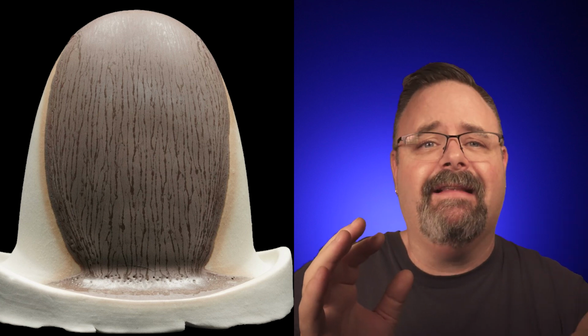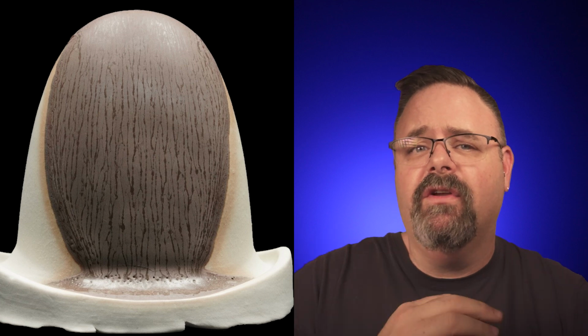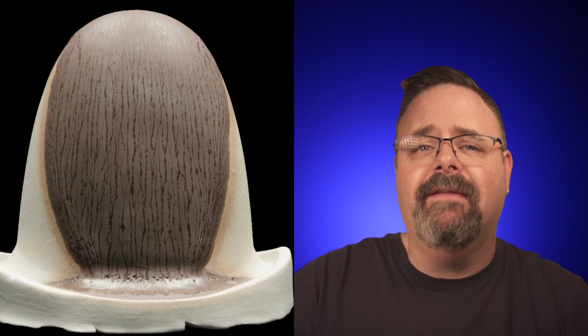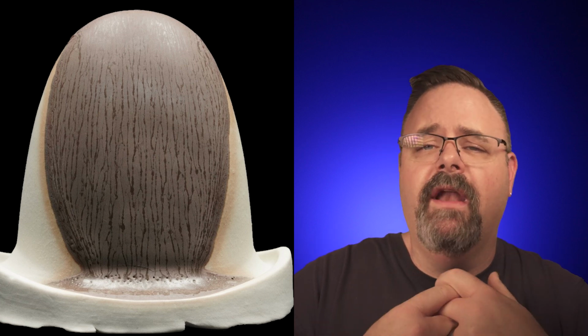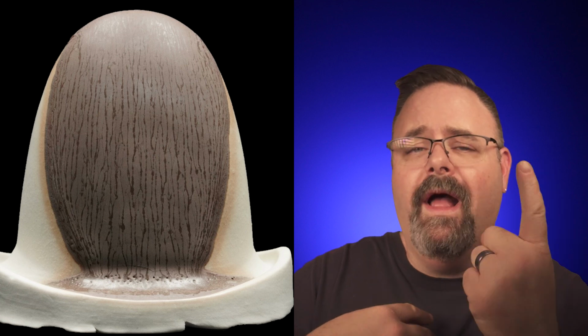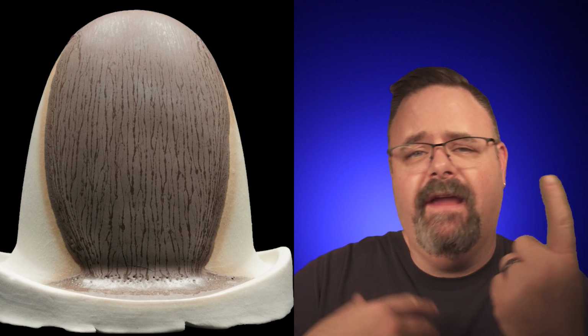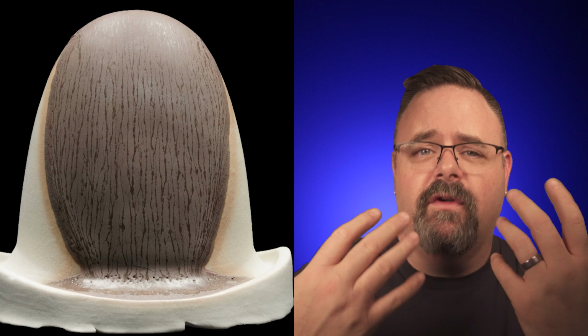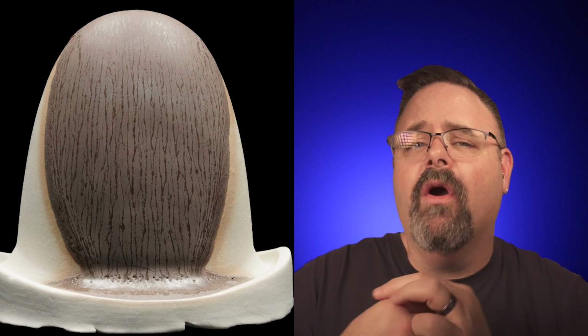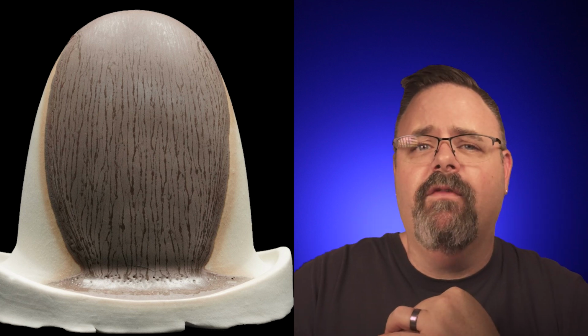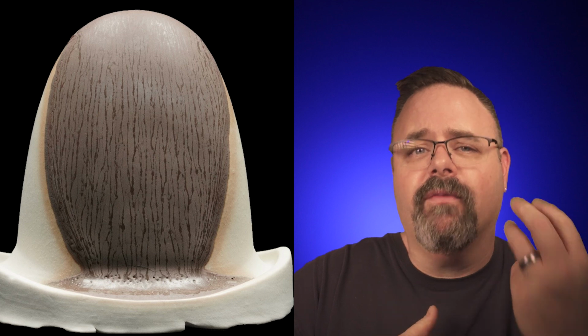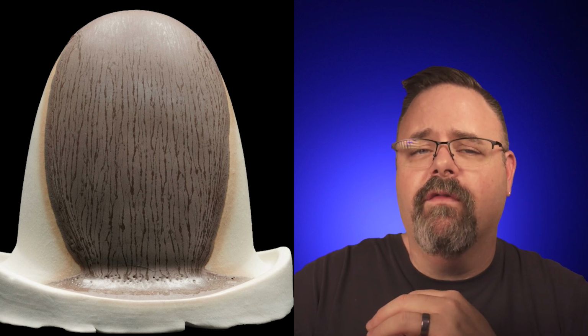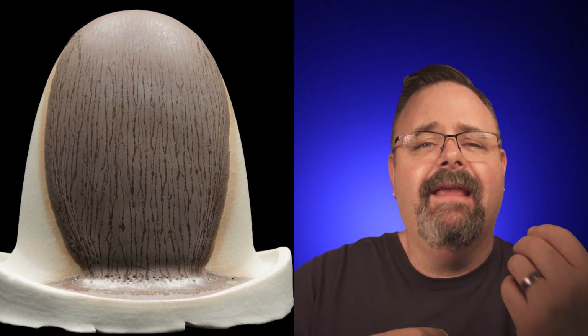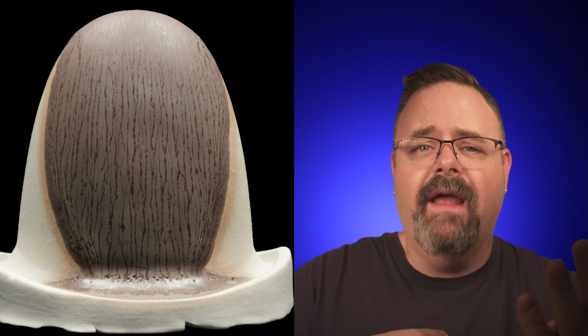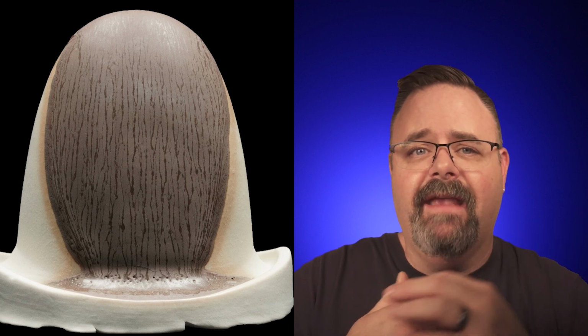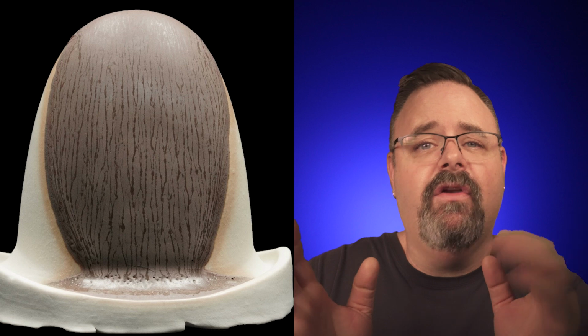We can see that this glaze ran, and that's actually a really good sign and fairly common with matte glazes, because glazes only run for three reasons. One, they are too thick. Thick is just gravity, right? Thick things are always going to move down to the earth. Two, they are overfired. Overfiring will force a glaze to run. And three, they are too thick and overfired. So if a glaze is fully melted, it can run, and it's being slightly overfired, which is the case on this one. And that's okay, but that's actually a good sign.